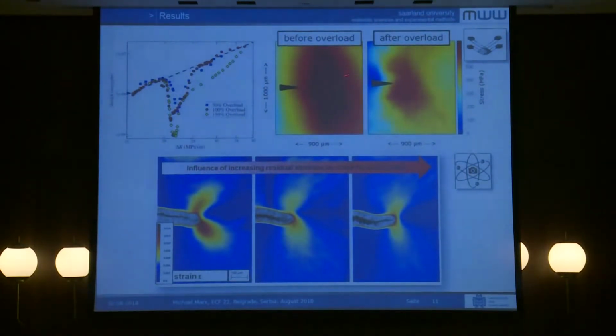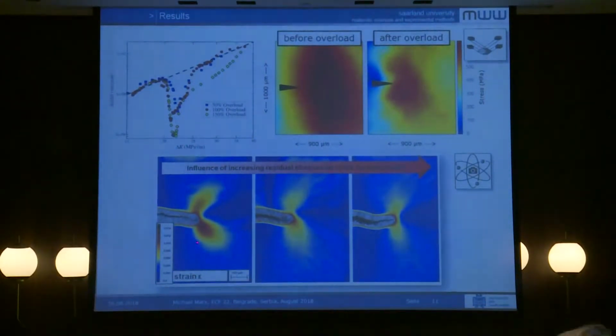Unfortunately now here in this image red means tensile and not compressive as before, so these here are now tensile stresses. So the maximum stress during loading is reduced after the overload due to the residual stresses, and you also find this in the strain field. This here is the crack after the fatigue, and you see the strain field at the fatigue load, and this here is after the overload. You see the crack opening displacement is increased.